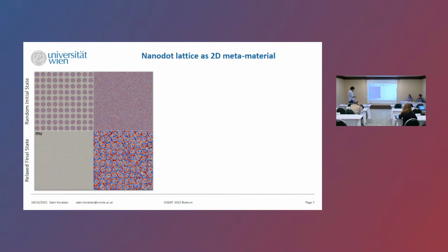If we relax the structures, then we can see that in the permalloy lattices, we are observing, of course, vortices. So we have chosen the critical dimensions for the permalloy nanodots to be able to host stable magnetic vortices. And you can see that we have blue and red dots. It will be a bit more clear in the next slides. But you can see here, if we don't apply any out-of-plane magnetic field, then the polarization of the magnetic vortex core can be either up or down.